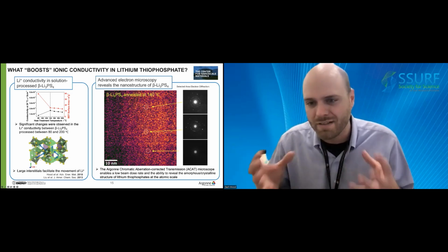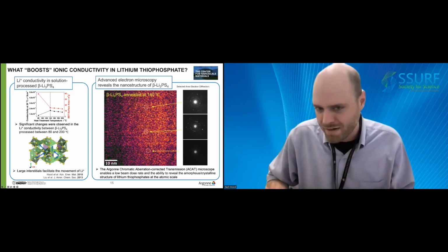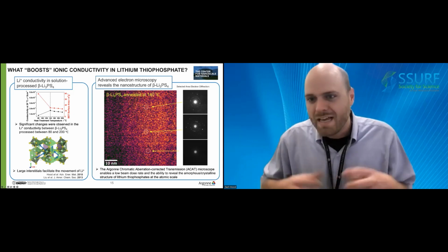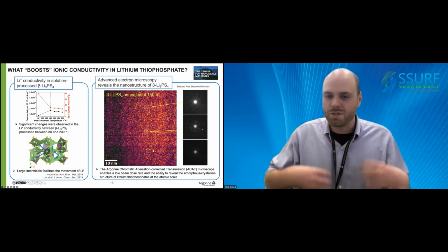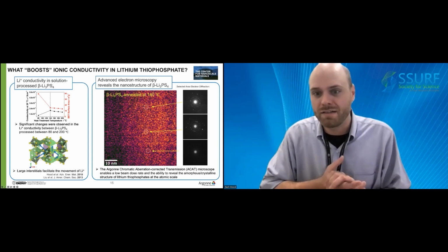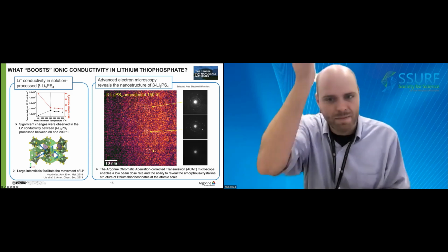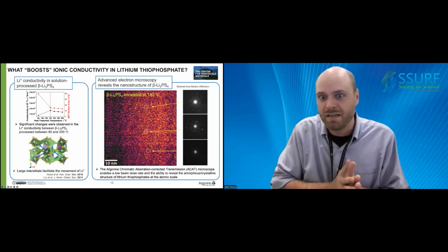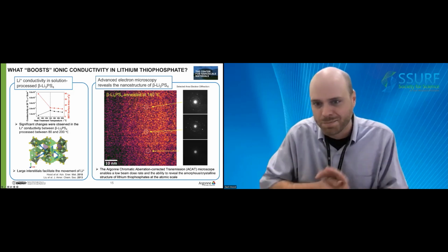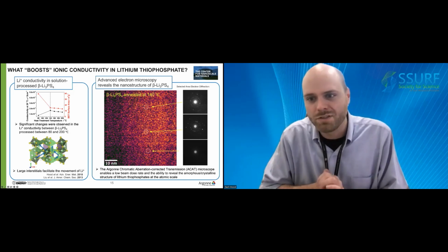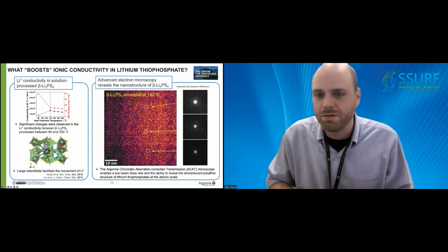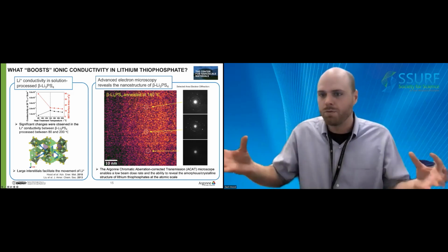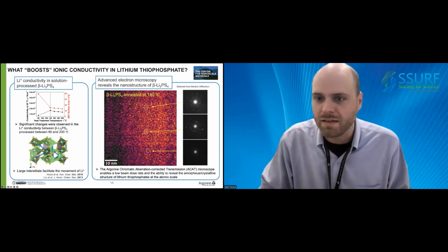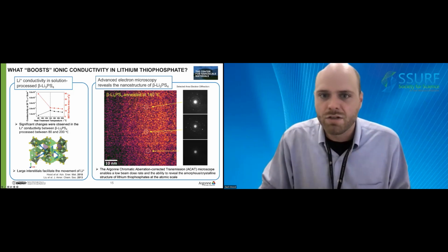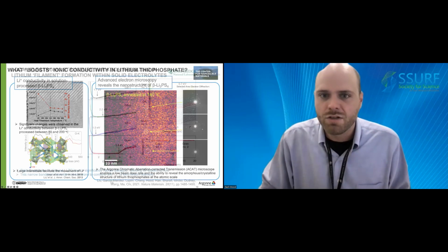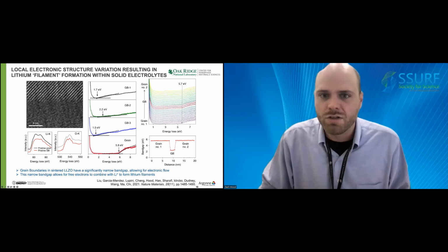This characterization allowed our team to better understand the phase transformation of these materials and the impact of crystalline size on the observed macroscopic ionic conductivity, or how fast the lithium ions can move through the crystalline and amorphous regions in the lattice. This result also reveals the importance of grain boundary chemistry on the macroscopic performance of solid-state electrolytes. And so, as mentioned in this previous example, grain boundary chemistry is particularly important for solid-state electrolytes.